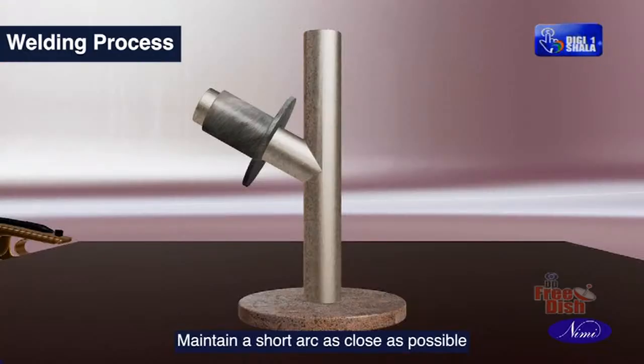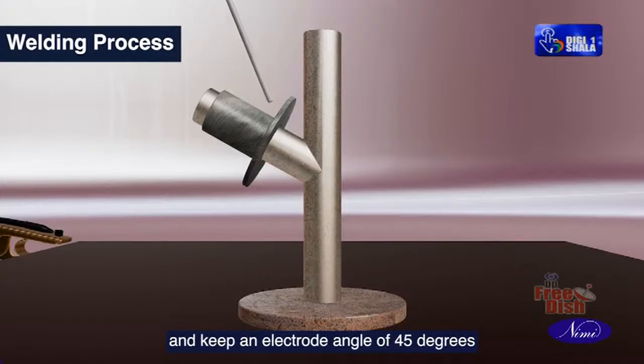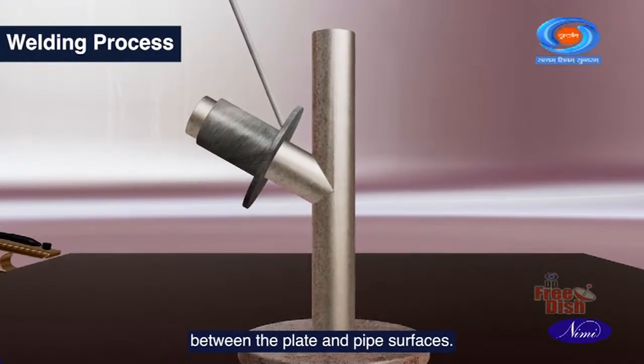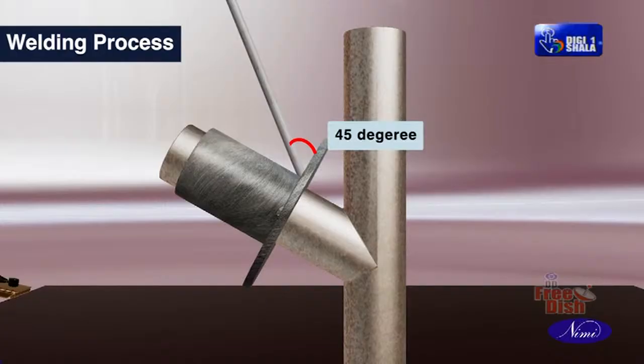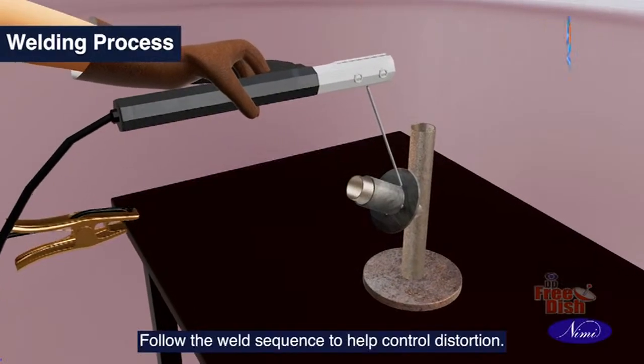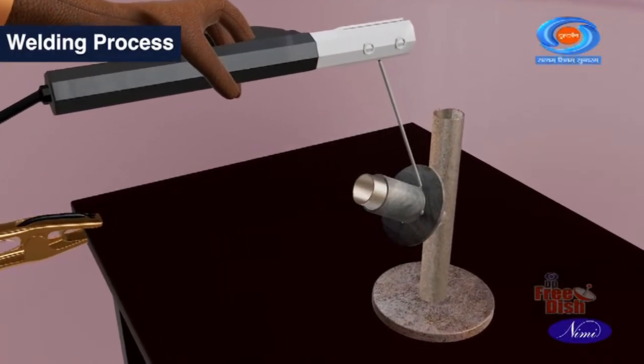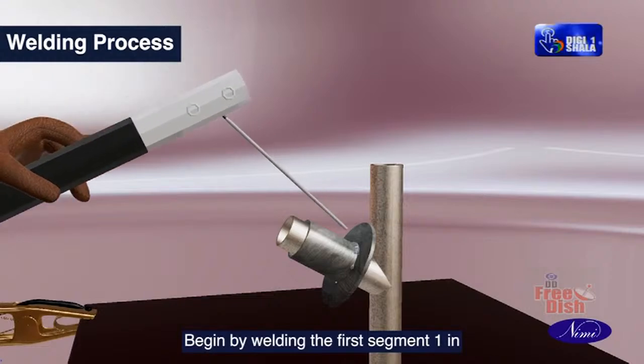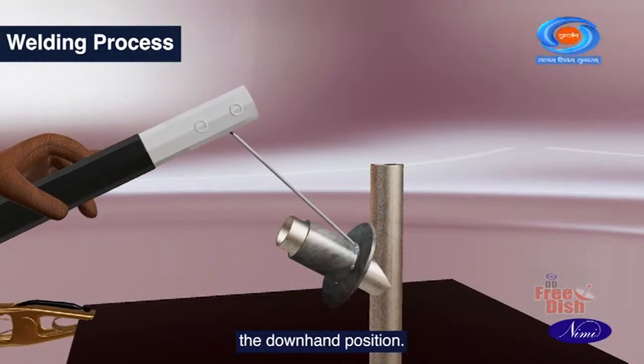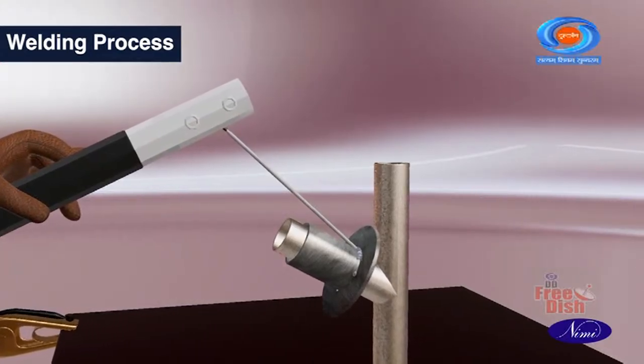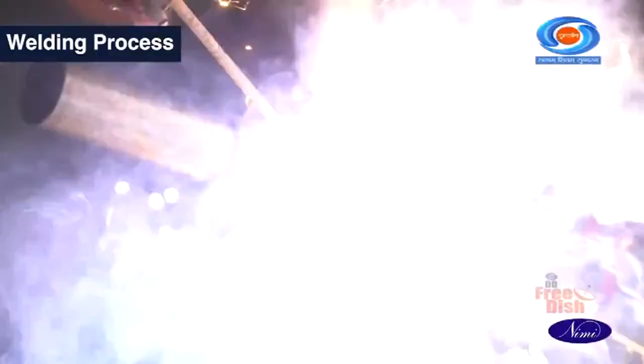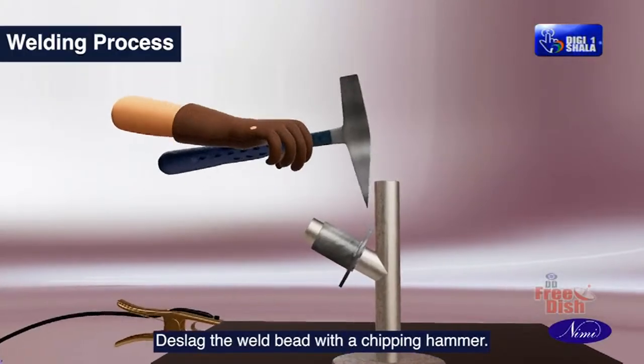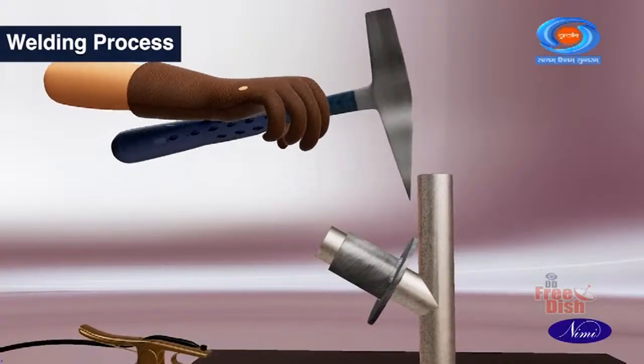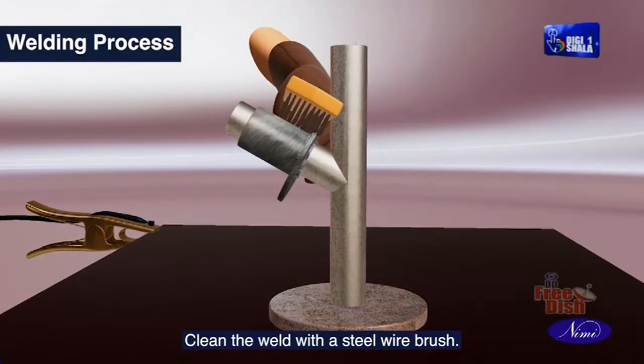Maintain a short arc as close as possible and keep an electrode angle of 45 degrees between the plate and pipe surfaces. Follow the weld sequence to help control distortion. Begin by welding the first segment 1 in the downhand position. Deslag the weld bead with a chipping hammer. Clean the weld with a steel wire brush.